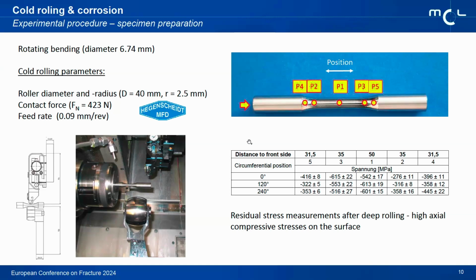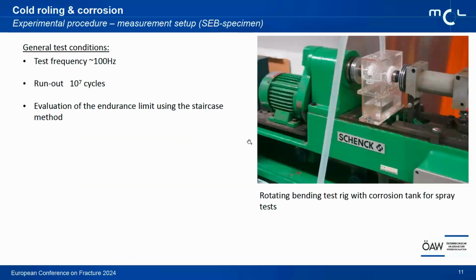from -276 up to -615. Okay, the prepared specimen were then tested in a rotating bending machine with a test frequency of approximately 100 Hertz. We defined the run-out as 10 to the power of 7 cycles and evaluated the endurance limit with the staircase method. Then here we applied this corrosion tank for spray tests.